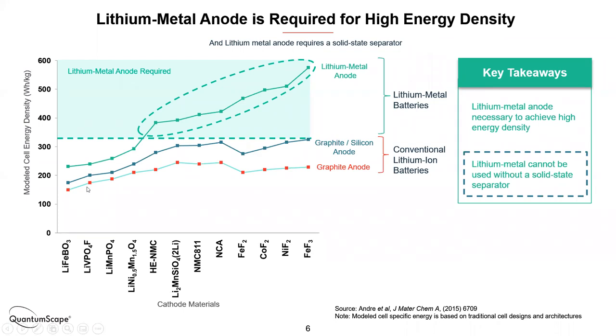And what you find is with today's anode, the graphite anode, you hit this ceiling of a little over 200 watt hours per kilogram. If you introduce some silicon, which is this second curve, you can do a little bit better, but as you continue to improve the cathode, you have to continue to add more and more host material, more and more racks for storage of the lithium ions in the anode, and you can never really get beyond about 300 watt hours per kilogram. On the other hand, if you use lithium metal, pure metallic lithium metal, you effectively do away with